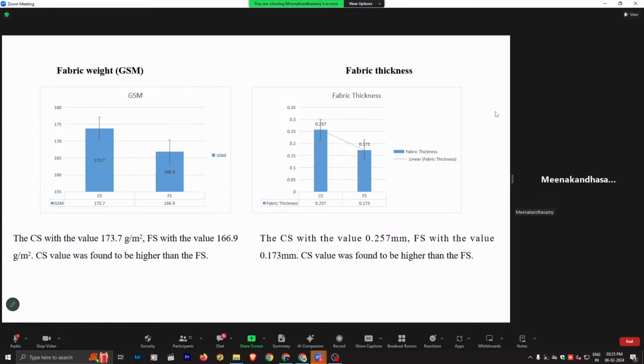Next, fabric thickness. It is observed that the fabric thickness shows variation between the control sample and the finished sample. The fabric thickness is analyzed using a t-test. The control sample has a value of 0.257 millimeter. The finished sample value is 0.173 millimeter. The control sample value was found to be higher than the finished sample.